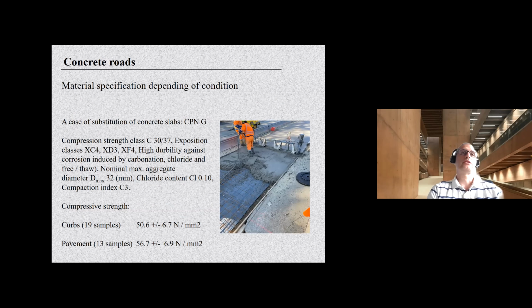We looked at some cases, and we saw a substitution of concrete slabs on a street about 400 meters above sea level. They used concrete with strength class C30, so 30 megapascal, with a high exposition class, so high resistance to carbonation, chloride diffusion, and freeze resistance, so in general high durability against these several corrosion types induced by CO2, chlorides and freeze-thaw.